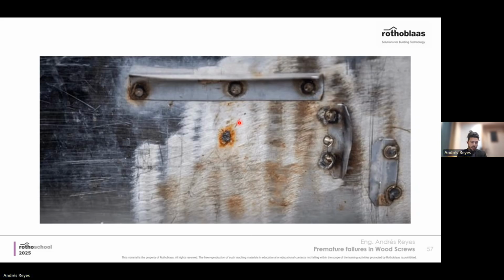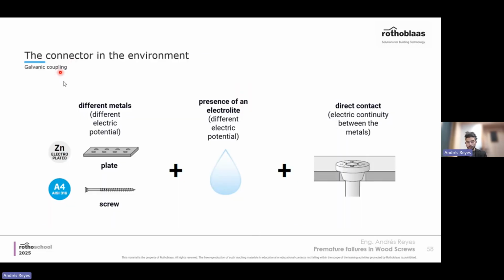It's not the only thing to consider. Of course, there's also galvanic coupling. This picture is not the best, but it illustrates corrosion happening around the screw. It indicates a difference in the metals, and thus galvanic coupling. Galvanic coupling only happens when three things are present. Different metals: if the metals are not different, there's no galvanic coupling. The presence of an electrolyte: indoor connections, even with different metals, generally don't have any problem unless there's water. And direct contact: if there's no direct contact, there is no galvanic coupling.